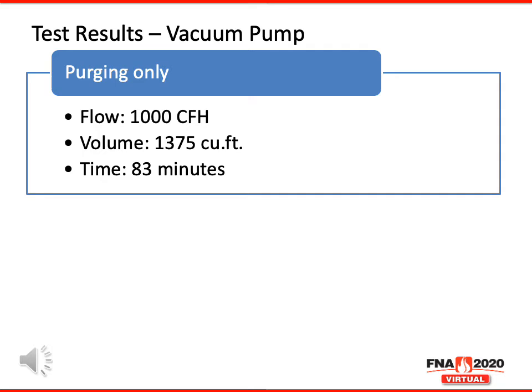First we're going to look at test results using a vacuum pump. So if we only purged the furnace using nitrogen, the furnace has an available flow of 1,000 cubic feet an hour. The total volume to be purged, which to meet safety requirements per NFPA would be 5 volume changes of the retort before being considered acceptable to add ammonia to the system. So we had to purge a total volume of 1,375 cubic feet. And so that's a time of 83 minutes to complete a single purge step.